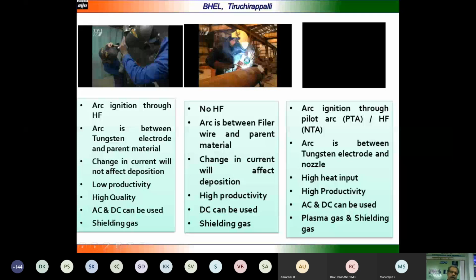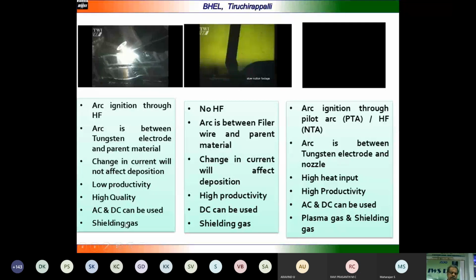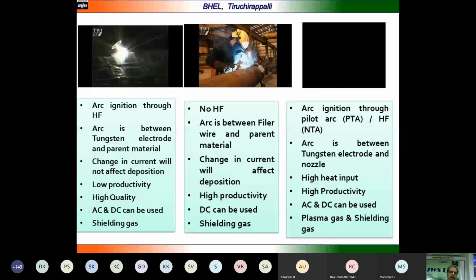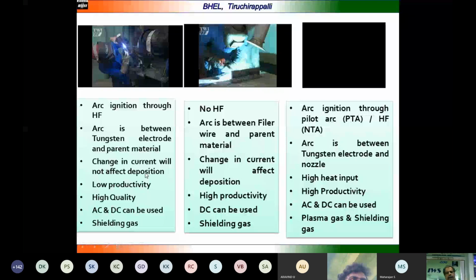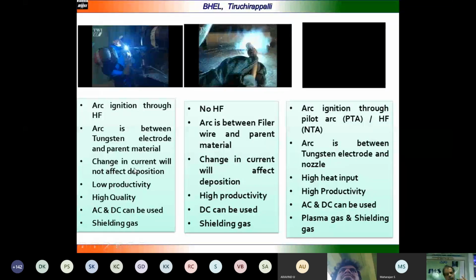Shielding gas is required. Argon, helium, hydrogen, or argon-helium can be used here, because helium will give deeper penetration, while argon will not give that much penetration. But the quantity of helium gas consumption will be more compared to argon in the case of TIG welding. So when you want high penetration welding, then you have to go for helium gas.